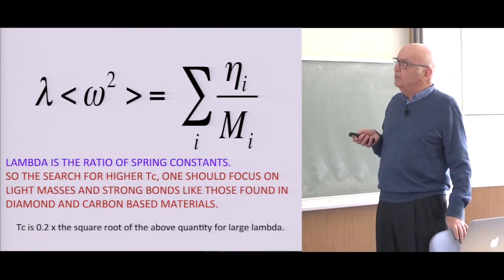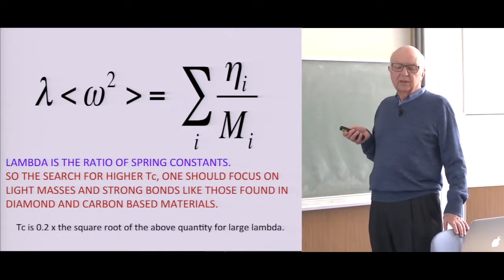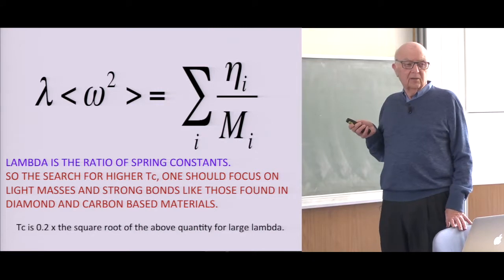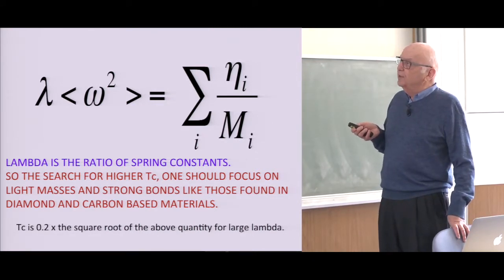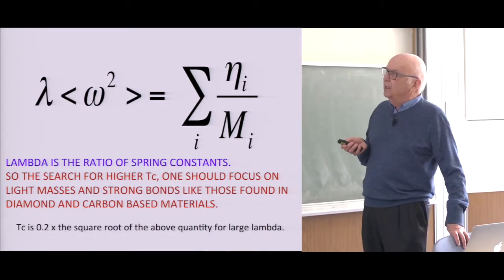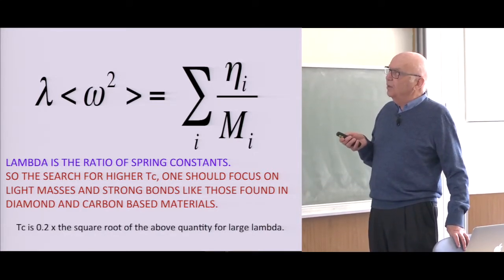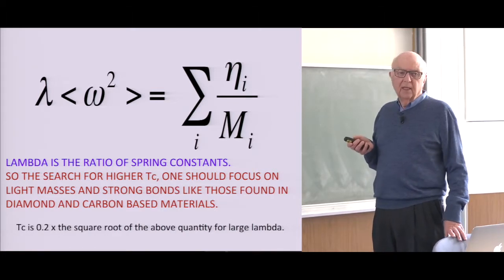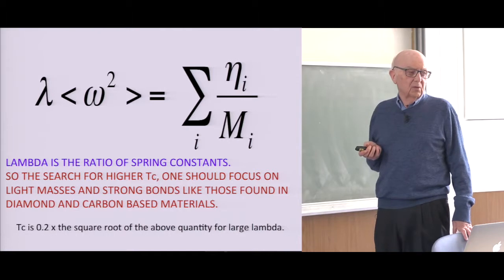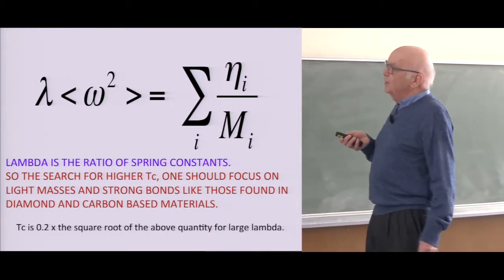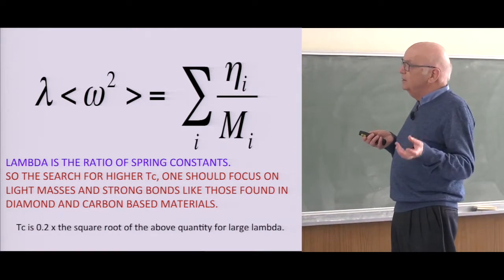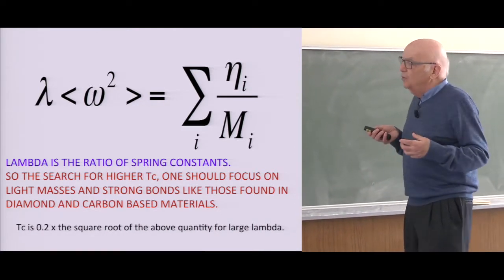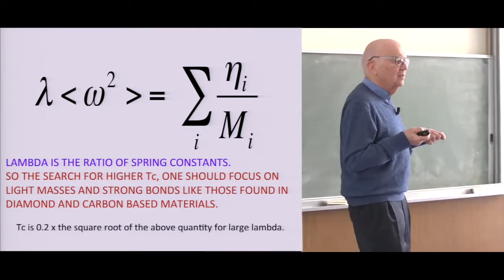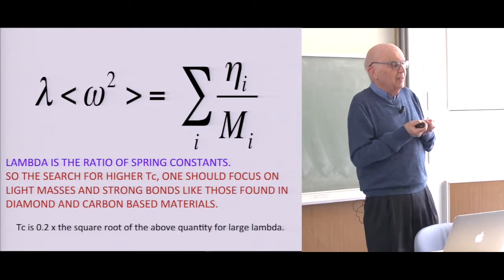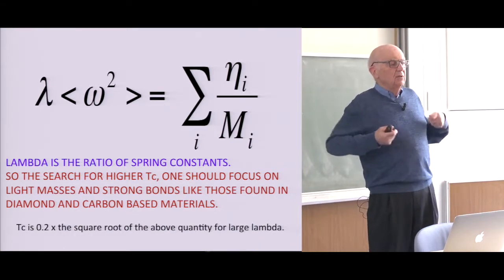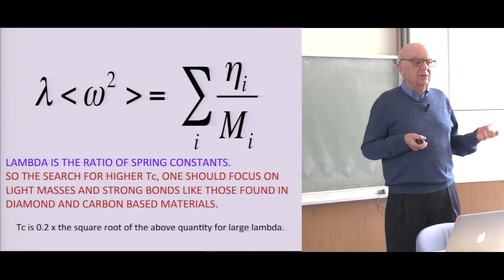So to get the largest lambda, you want to have a small lattice spring constant and a large electronic spring constant. Now, the reason I wrote it this way, so lambda is the ratio of the spring constants, is if I take this quantity and take the square root and multiply by 0.2, that's the superconducting transition temperature. So it's a simple formula, but it tells you that you want strong bonds and like masses, and you would want systems where the bonds are strong, like in diamond. But the trouble with diamond is that you have no free carriers. So you need to get carriers into diamond. So we were pushing to try to get carriers into diamond.